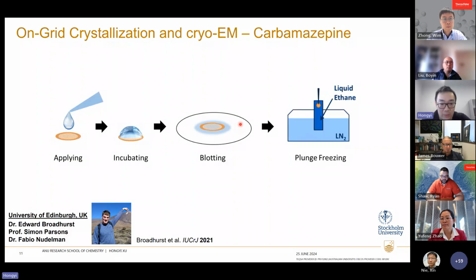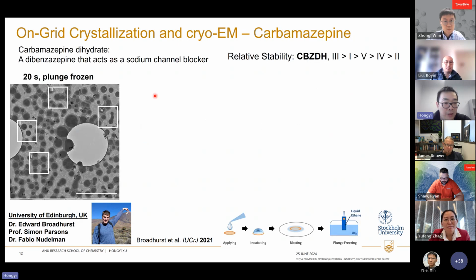Right, and the next experiment is a little bit more creative. So we were trying to see if we can crystallize a certain compound of a small organic molecule on the grid and then follow the crystallization process with MicroED. So we apply the solution of the compound and then incubate it for different amounts of time, blot away most of the liquid, and then freeze the grid to look at what was trapped at this time point during the crystallization process. And this was after 20-second plunge freezing.